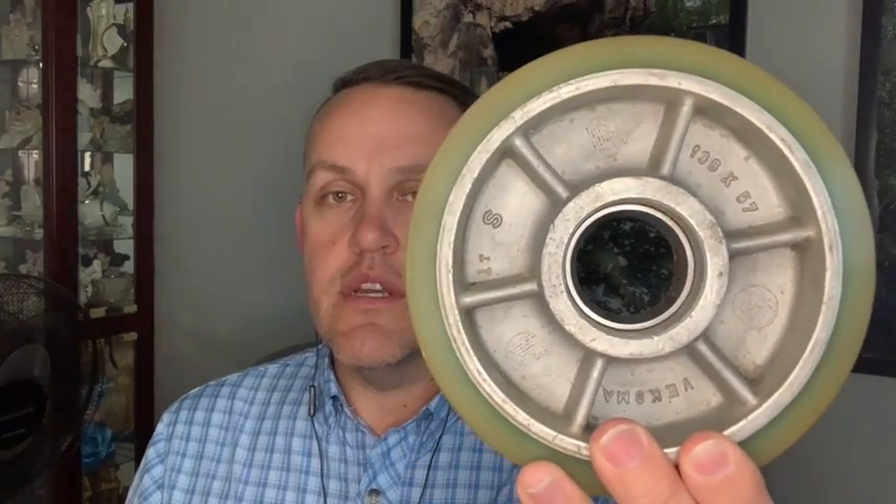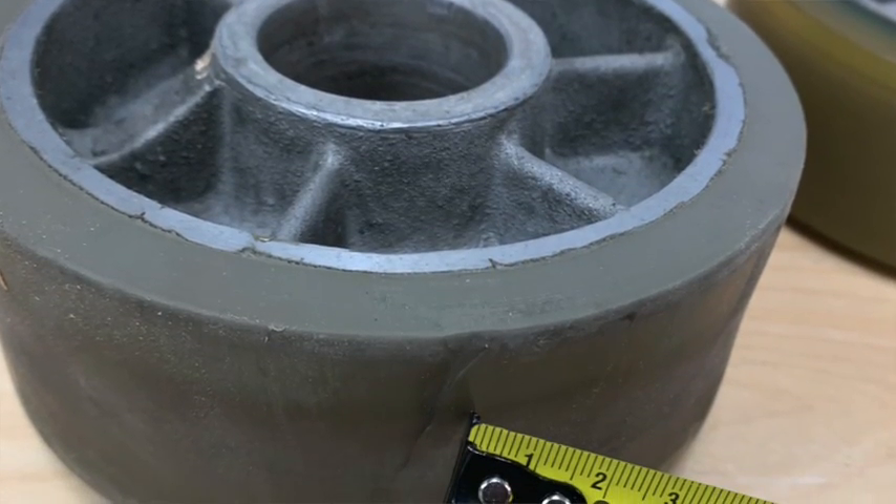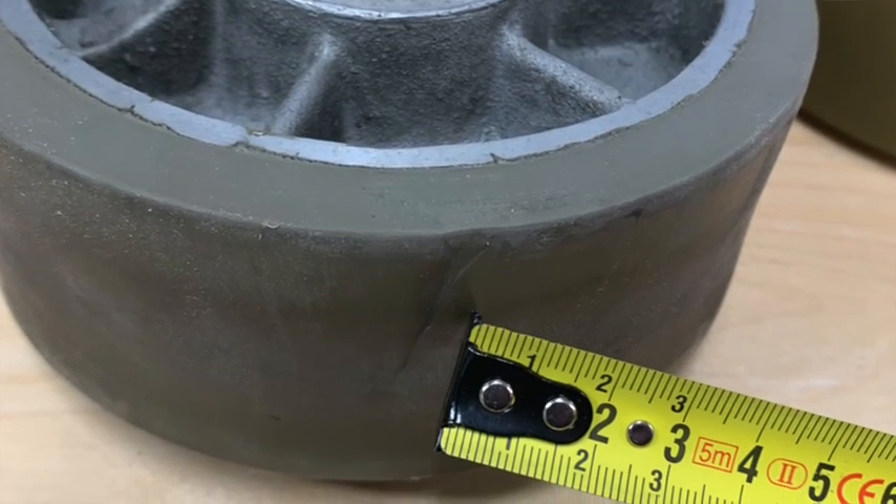Here's a wheel — right here. This is a guide wheel off of an SLC. When we inspect this wheel in the morning, the main thing we do is turn it all the way around the surface and look for cracks — little chips and cracks. Typically what happens is that the wheels start to crack on the loading surface, meaning it cracks right here on the face. It'll look like a black straight line going across it, and you can actually let that ride for a long time depending on the ride's severity on the track. This can crack right there and start going all the way out to the side, and once it reaches the side of the wheel and turns down on this corner, that's typically when it's like — okay, we're going to have to replace this wheel soon.